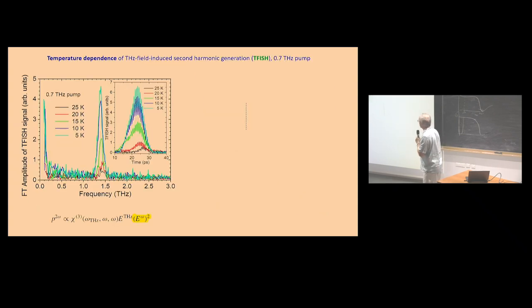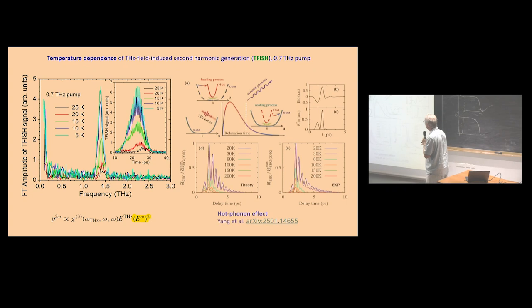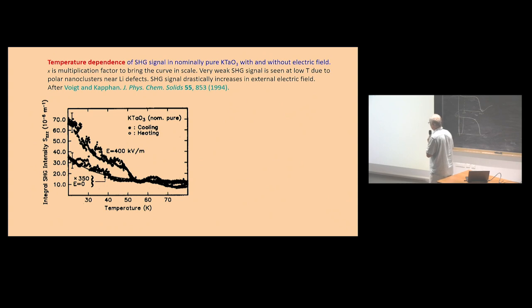We also measured second harmonic generation, THz-field induced, in strontium titanate at low temperatures. We see the effect, but it will probably be better to explain it by this hot phonon effect. This paper is still in progress. But it can also be mentioned that second harmonic generation in potassium tantalate was also measured classically in a crystal.